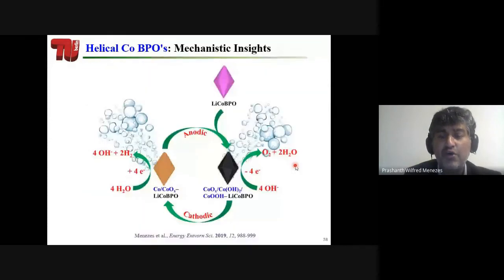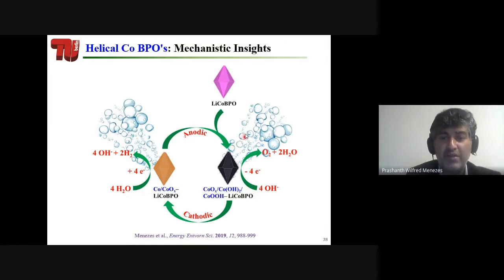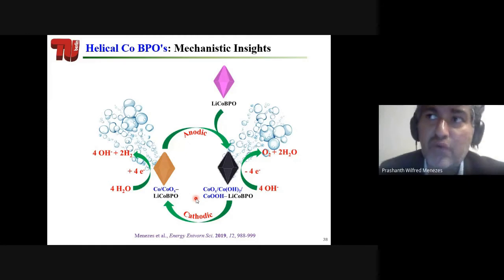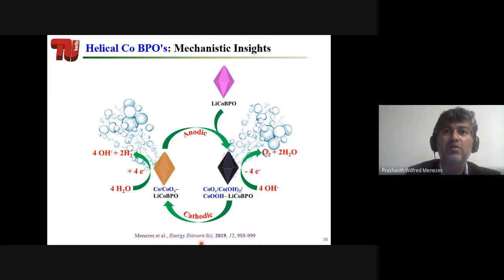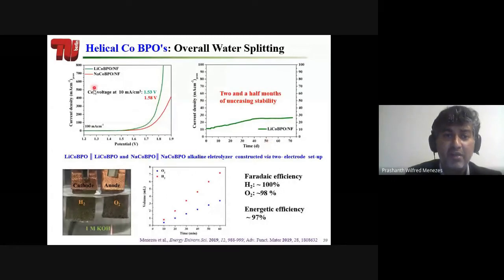Okay, so finally, to conclude, we have a lithium cobalt borophosphate, which is the initial nice structure. If you apply oxygen evolution potential, you change the structure into something like cobalt oxide, oxyhydroxide on top of lithium cobalt borophosphate. Similarly, if you apply hydrogen evolution potential, you are forming metallic cobalt and oxide on top of lithium cobalt borophosphate. This is somehow a general rule. If you take a catalyst in oxygen evolution reaction or hydrogen evolution reaction, your catalyst changes. That's the whole point.